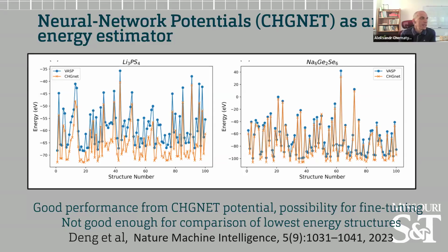It's not ideal, in the sense that when we compare small energy differences between our candidate structures, we do not find the same order of structures as in the DFT calculations. But there we are talking about meV differences per atom. When we are talking about larger differences while sampling the phase space, then CHGNet is more than adequate to tell us whether it is worth looking in that particular region of space or absolutely not worth it. And so our current implementation of the code, when we are running the simulated annealing, uses CHGNet as an energy evaluator. And when we go into the local optimizations, that's where we employ DFT as a more accurate technique.